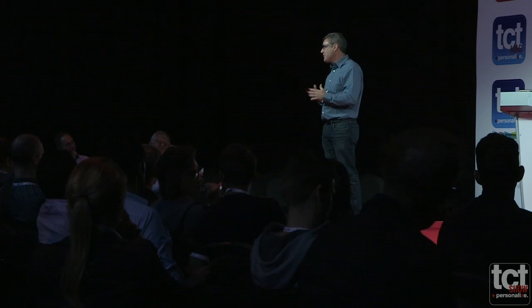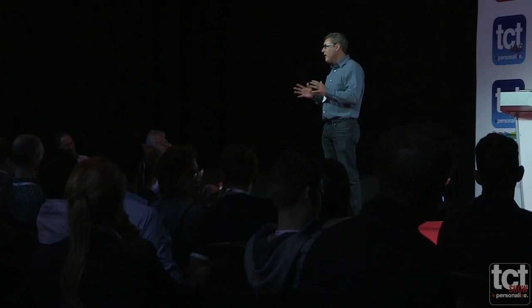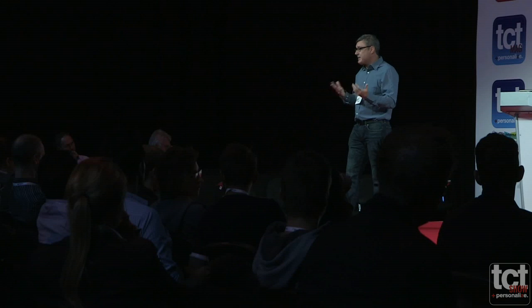So when we assemble our builds, those are the sorts of strategies that we look to when we're putting things together. And there are also other sort of economies that we look at as well. I mean, if we can increase our layer thickness without sacrificing too much detail, say we go from 100 microns to 110 microns, we've immediately knocked out 10% of the layers that we have to build, and that's a corresponding increase in utilisation of the machine and our building efficiency. So we look at a whole range of different things to try and optimise and make as much stuff as quickly as possible with the platforms that we have.